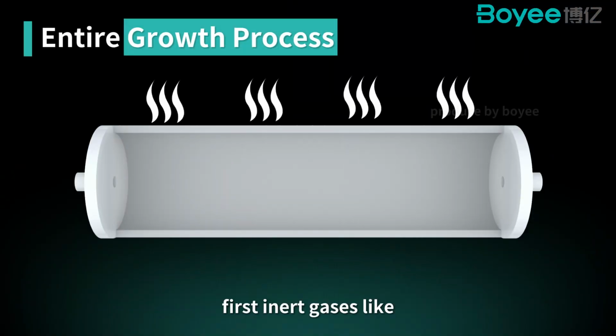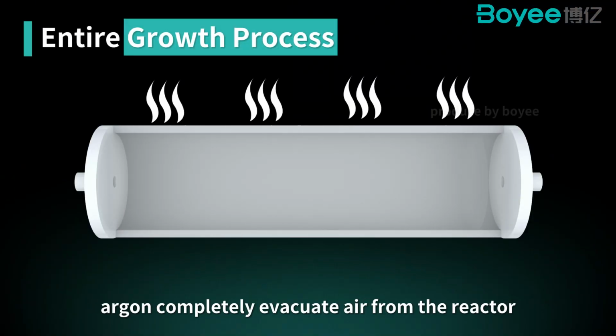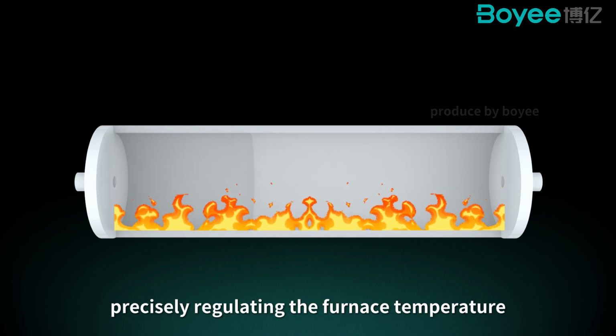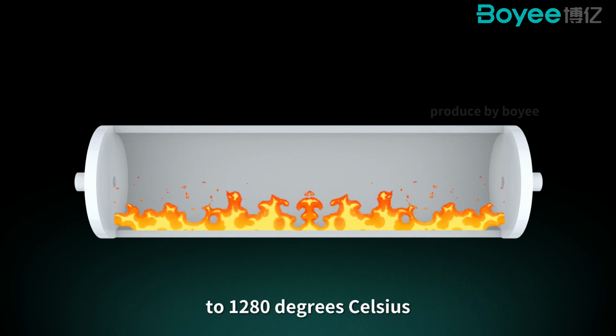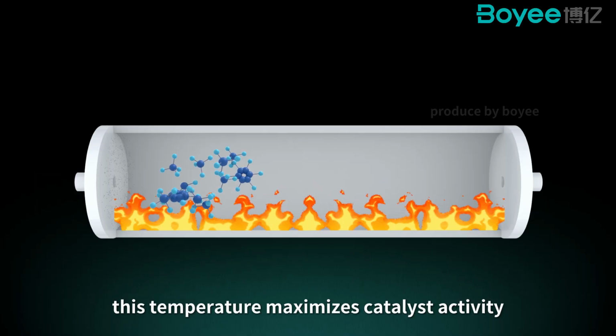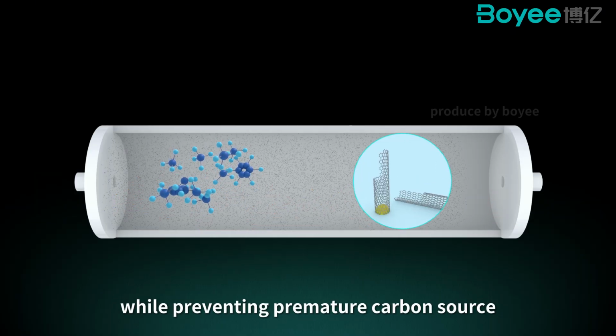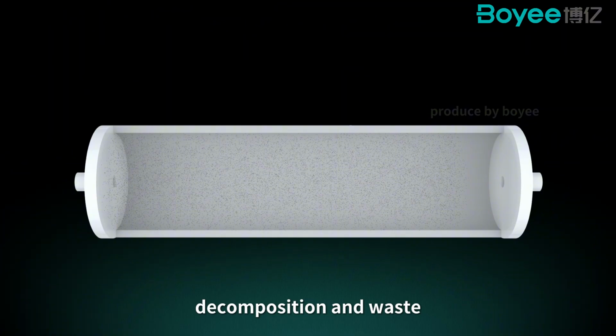First, inert gases like argon completely evacuate air from the reactor, precisely regulating the furnace temperature to 1,280 degrees Celsius. This temperature maximizes catalyst activity while preventing premature carbon source decomposition and waste.